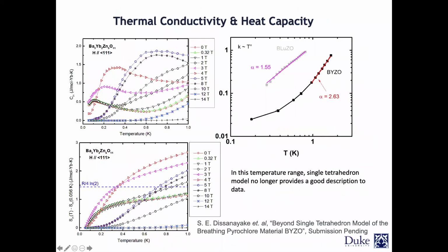Again, we also looked at the heat capacity data. For the heat capacity, it shows that there is something going on at low temperature. So look at the temperature here. This is 1 Kelvin. We went down to 50 millikelvin, and this is as a function of field. So even at 0, you can see that there is a broad feature. The fact that it is broad shows that it is not going to have a long-range order, right? There is something else happening. So we still do not understand exactly what is going on. But if there are any quasi-particles, here it is showing itself.